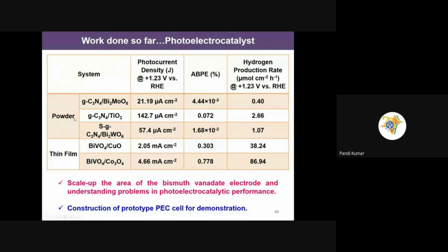strategies. We synthesized the material in powder form, coated it over the electrode, then explored the photoelectrochemical performance. You just look at this, the hydrogen production rate values are very low, and the efficiency is also very poor. Upon introducing the thin film fabrication strategy, you can see the values are very close to 1, almost 40-fold higher for the thin film. So we conclude that the fabrication of thin film based technologies is promising for green hydrogen production.